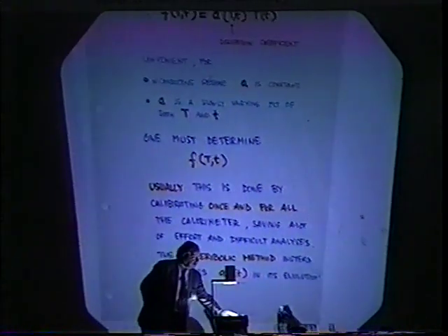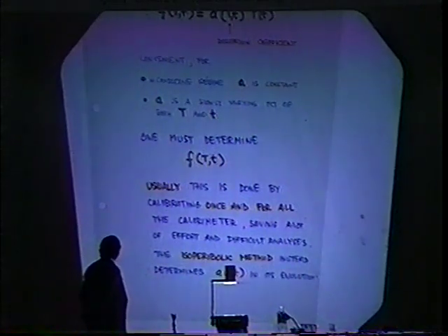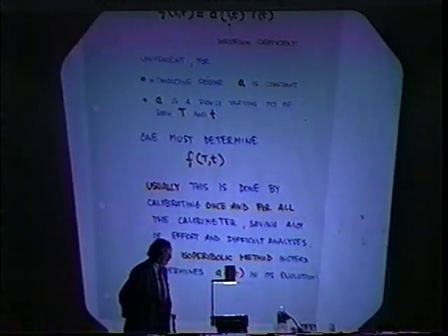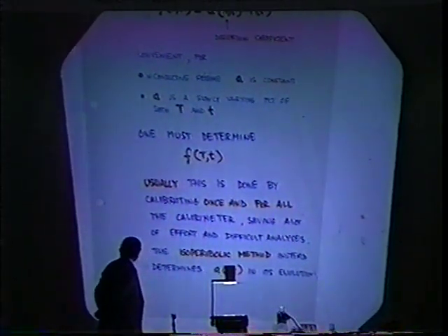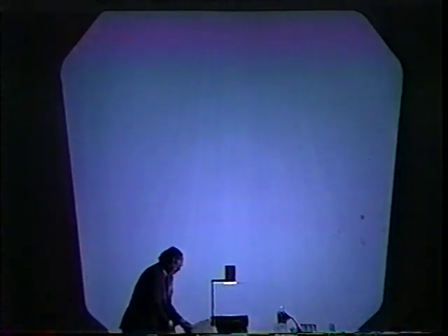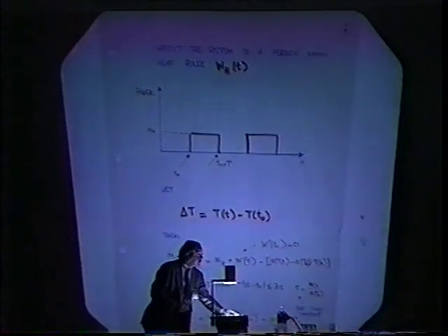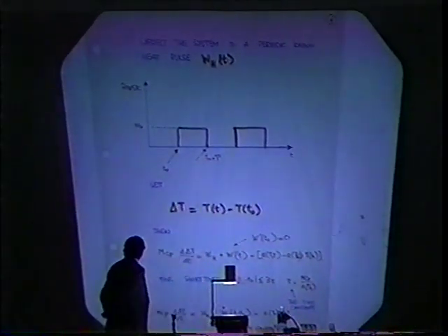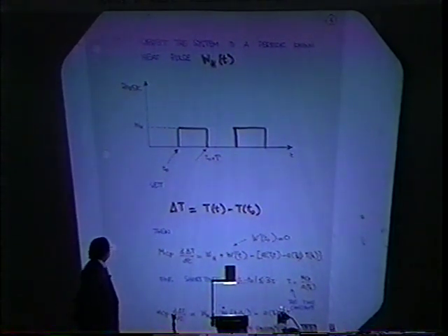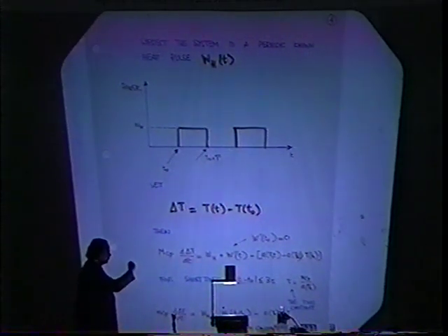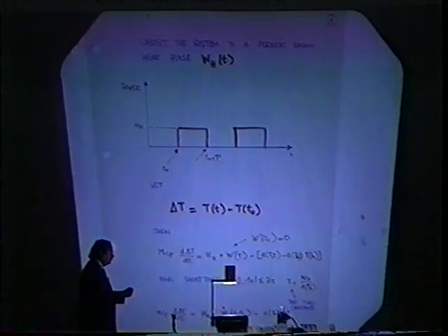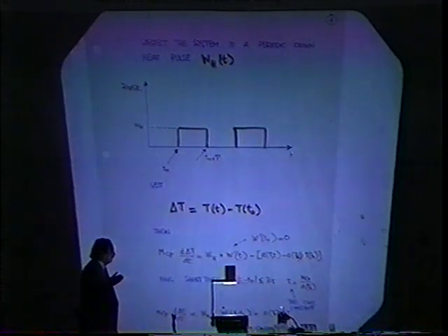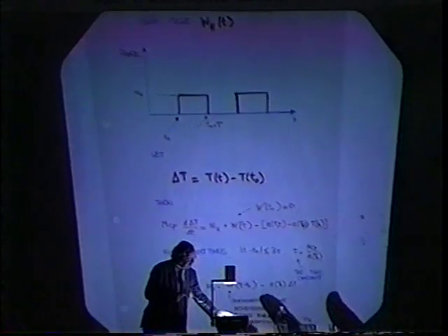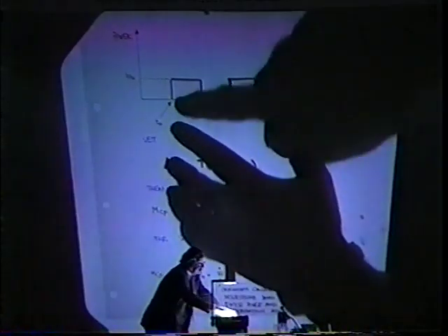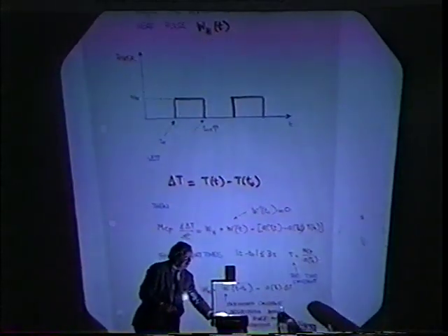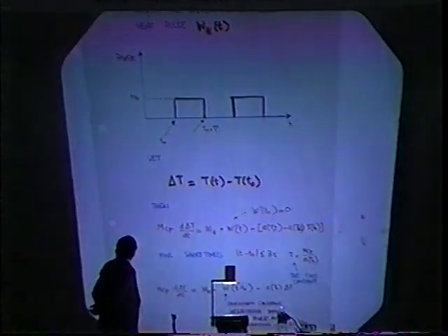Now, usually one tries to do this by calibrating once and for all this function, and in this way one saves a lot of effort and difficult analysis. The isoperibolic method instead uses periodic heat pulses, a very well-known characterization. These heat pulses are essentially perturbations. They must be a small fraction of the input power, with discontinuity and periodicity. This is a very good idea, because then you study the transient of the temperature profile of the calorimeter just when you switch on and when you switch off these heat pulses.